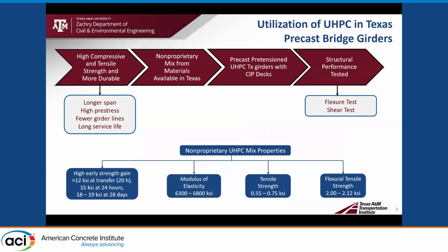To give an overview of the mix developed at Texas A&M University, we got high early strengths of 12 KSI at release, and about 18 to 19 KSI at a later stage. A modulus of elasticity of about 6,500 KSI and a tensile strength of 0.625 KSI. I would like to point out that we were using 1.5% fibers by volume when compared to the usual 2%. This also reduced the cost. We got a high flexural tensile strength of about 2 KSI.